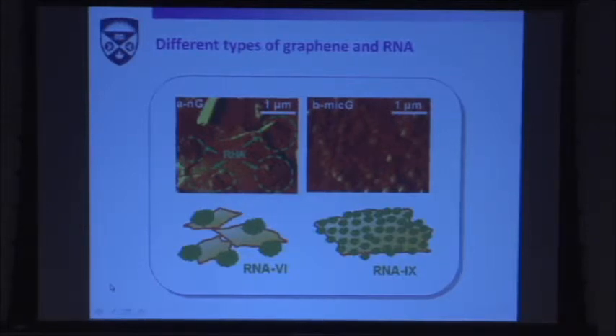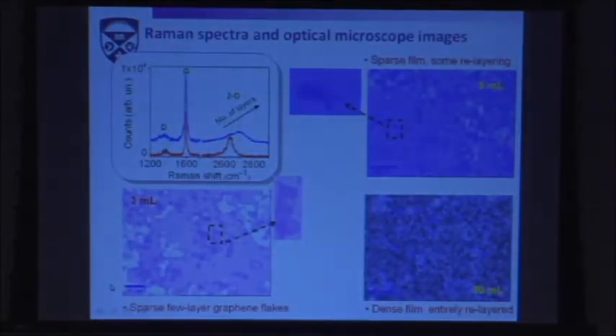And this creates, in this case, a buoyant force that keeps graphene suspended in water, and at the same time, this intercalation of RNA into graphene favored its exfoliation. So it's a pretty nice job. Again, if you use Raman as a check, you find out that when you vacuum filtrate just one layer of this suspension, you have single layer graphene with this 2D peak that I was considering before.